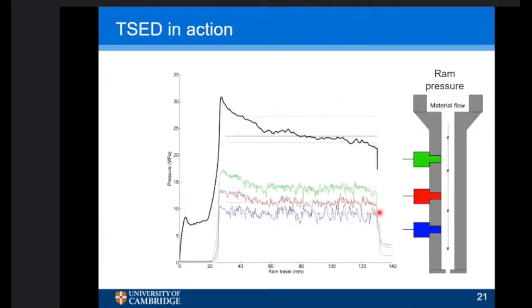And this is an example of what you might see in terms of the ram pressure. That's the force divided by the cross-sectional area against the distance that the ram has traveled. So it pushes material down here and it flows along there. And this is the extrusion pressure that the ram is measuring. But of course, that has to include the change in area as the material flows from the barrel into the primary die. And then we have the green, the red, and the blue.